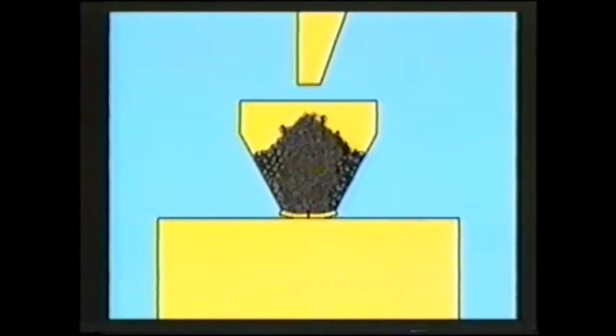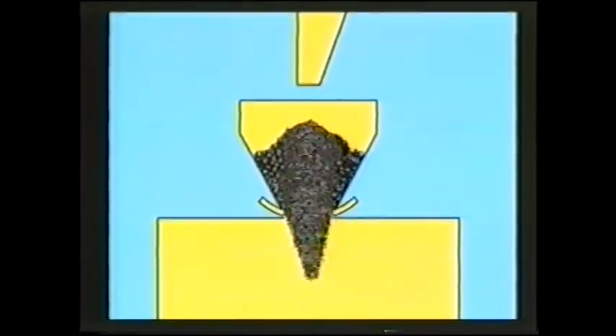As these small amounts of material fall to the center of the slug feeder, a coned pile is formed. This is where the trouble begins. The finer material tends to remain in the center of the pile, while the larger aggregate tends to roll to the side. So segregation has already begun. When this material is batched into the silo, it goes through a round discharge opening in the center of the slug feeder. As the finer material is discharged first, the coned peak becomes inverted to form a funnel or rat hole. Then the larger aggregate, which had collected around the outside, rolls to the center and goes in last, causing secondary segregation.